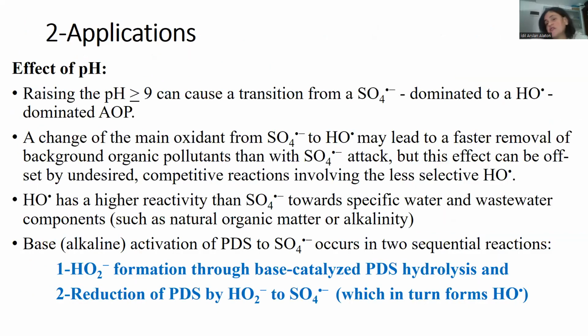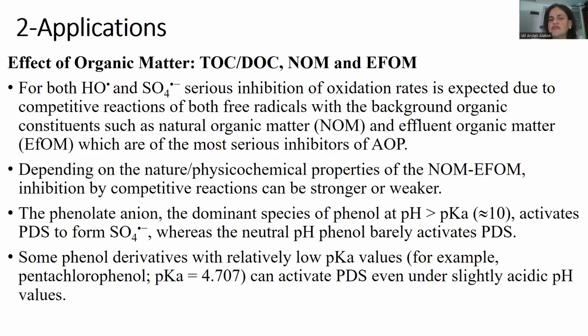Here, the pH can be important, has an effect, as we have already mentioned, because it can cause a transformation of the active oxidant from sulfate radical to hydroxyl radical, so that more hydroxyl radicals are involved at alkaline pH. The alkaline activation of PDS is also possible. Sulfate radicals are formed by catalysis and hydrolysis reactions, and the reduction of peroxidized sulfate, for example, by hydroperoxide ions to sulfate radicals, which in turn can form hydroxyl radicals.